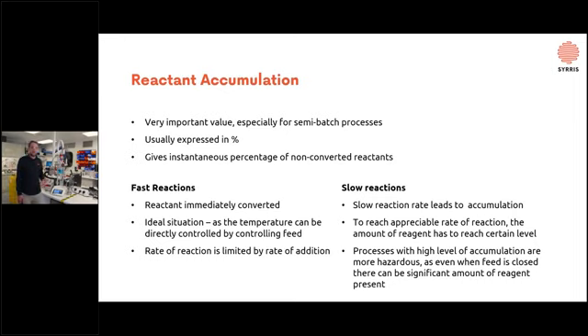There could even be a situation where the kinetics are such that we have to add quite a lot of reagent before our reaction takes place. And the rule of thumb is that processes with a high level of accumulation can be more hazardous, because even if we stop the dosing, we still have quite a lot of unreacted reagents which will still release heat, which can lead to a potential thermal runaway.